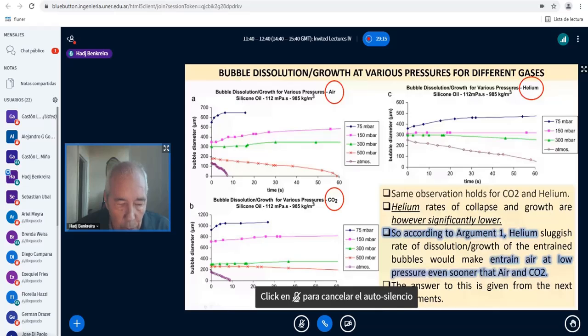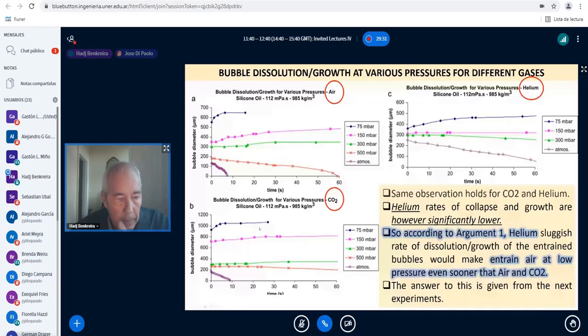With CO2, at atmospheric pressure, boom, collapse. At 500, it takes longer. At 300, it stopped collapsing. At 150, instead of collapsing, they grow. At 75, they grow. And observe that the rate of growth and the rate of collapse for air and CO2 are pretty similar. However, for helium, it's very different. It takes much, much longer. So the helium rates of collapse and growth are significantly lower.